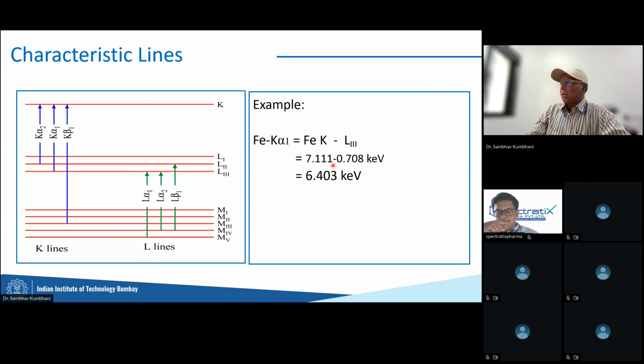In real numbers, when I say K alpha 1, like I said, it is the most common one. So for a K alpha 1 of iron, what happens is something from L3, which is at energy 0.708, reaches K, which is 7.11. What is left is 6.4 kilo electron volt. And this is a very, very specific number to iron K alpha 1 only. No other atom, no other element will have this exact energy. Okay, fluorescence energy, I mean.